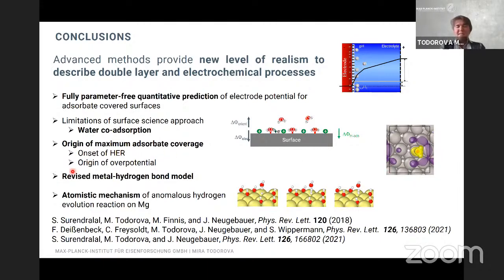In the end, I discussed the atomistic mechanism leading to the anomalous hydrogen evolution on magnesium, and also showed you that we can really start to look at dissolution processes as we drive the system, if we can potentially control the system. And all this work can be found in these three papers.